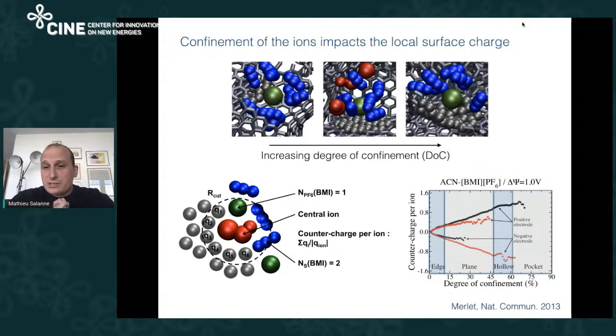And then you start to have a large degree of confinement. What we showed in the study is that, when you go towards larger and larger confinement, you start to have larger charges on the carbon atoms. And this is the reason why, for example, in planar graphite, you will never reach the same capacitance as you can inside the nanoporous materials.